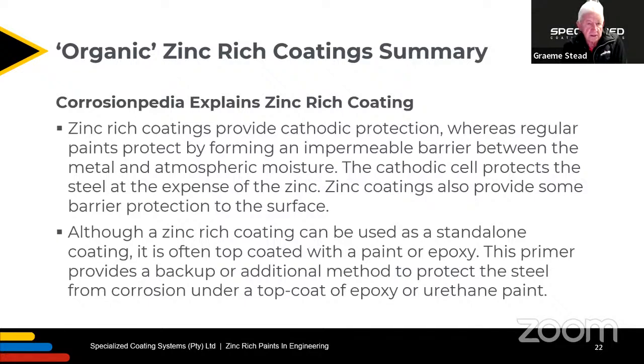I emphasize that the surface preparation must be as good as possible, and the surface profile should not be too high. I would say 50 to 70 microns maximum, depending on the final specification. Cleanliness, lack of oil on the surface, lack of dust on the surface. One needs to get the zinc particles in contact with the steel particles as quickly as possible.